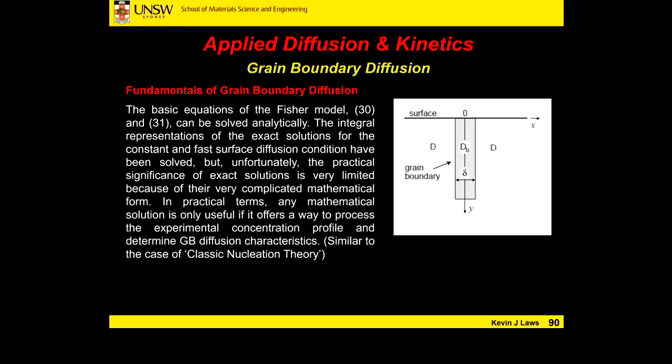Well, we physically have to cut it up and measure the amount of carbon over our depth profile. So it's a very physical measurement, and we're trying to tie that back to a fundamental equation. Once we have numerous data points, we can start to see, if I'm diffusing for this amount of time at this temperature, I get this depth profile. The width of my grain boundaries I can also measure. Okay, we can plug it back into this equation.